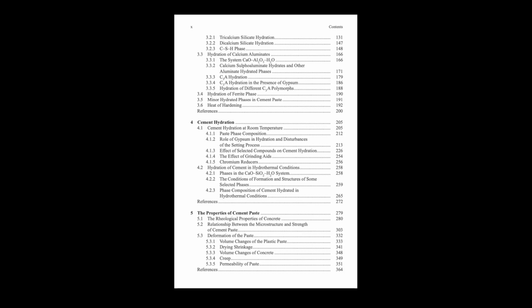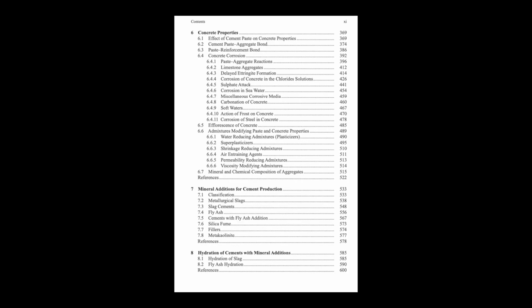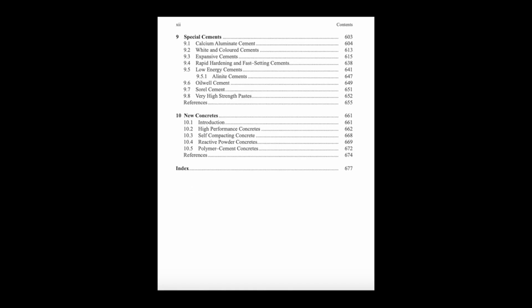And it affects how the CSH grows? Yes. Interestingly, studies show that with calcium chloride, the CSH growth direction on tricalcium silicate particles is modified. How so? Instead of maybe forming a dense layer that slows things down, calcium chloride seems to favor growth perpendicular to the surface. Leading to a more porous structure initially. Possibly, yeah. Allowing hydration to continue for longer, perhaps. But there are big drawbacks with calcium chloride in reinforced concrete, aren't there? Oh, absolutely. Huge drawbacks. Despite accelerating strength gain, it significantly increases the risk of steel reinforcement corrosion.